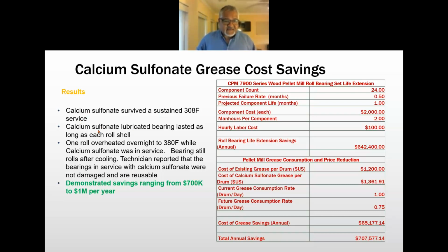Our calcium sulfonate lubricated bearing has lasted at least as long as each roll shell. As a matter of fact, they're lasting longer. They're still in great shape after 1,000 hours of service. Another good point to point out is that one of the rolls overheated overnight to 380 degrees Fahrenheit while the calcium sulfonate grease was in service.